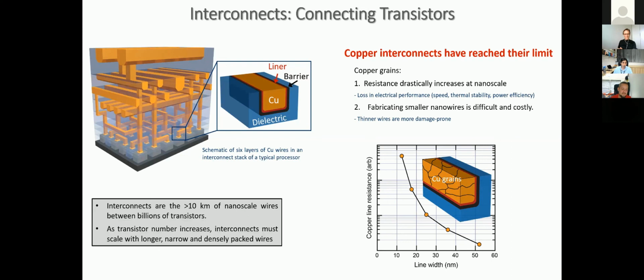Okay, what is the problem with the copper? Why can't you just keep making copper smaller? Well, as you shrink it, the resistivity of copper shoots up. And it's not just going to shoot up because your cross-sectional area is reducing, right? It's not just this classical Ohm's law scaling with the area. That is the normal increase that we expect. But then there is a huge logarithmic or exponential increase associated with these copper grains.